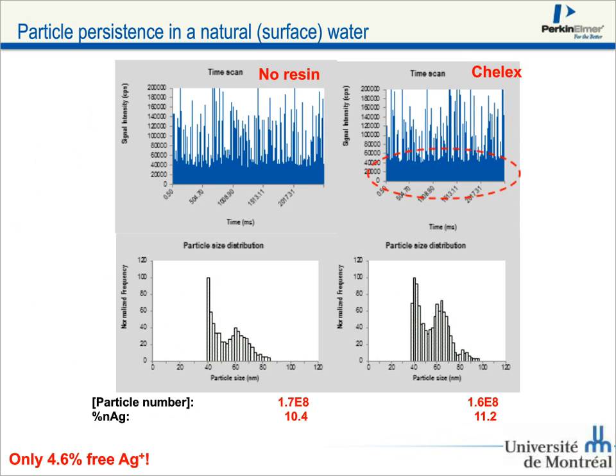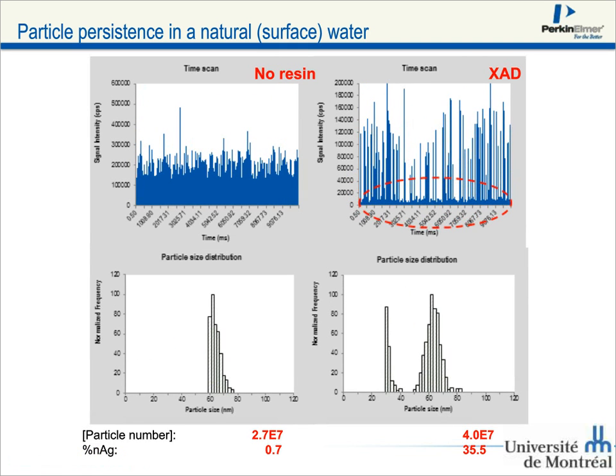If we do this in natural waters, you'll see it's not quite so easy. In this case, on the left-hand side, we haven't run through a resin. The right-hand side, run through a Chelex resin, and because there's so little free silver here, the Chelex resin doesn't really help us a lot. Most of the dissolved silver, in fact, it can be seen in the next one, was likely bound to organic complexes. By swapping out the Chelex for an XAD resin, we can remove that dissolved silver, get a much better particle distribution, and at the same time get some information on the nature of the chemical species in the solution.